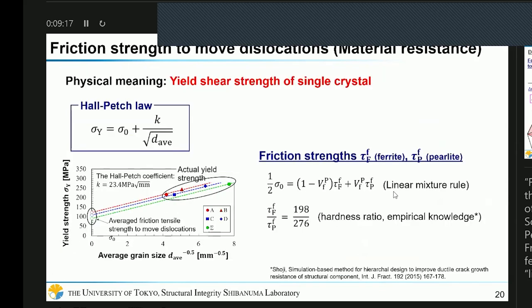The friction strength to move dislocations is a kind of material resistance in this model. And its physical meaning is the same as the yield shear strength of a single crystal. So we can estimate it based on the Hall-Petch law. Friction strengths of the phases, ferrite and pearlite, can be separated based on the linear mixture rule like this.